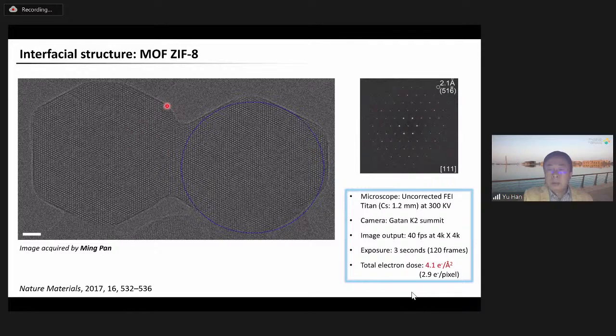Okay, in the previous slides, I showed you that under the normal conventional TEM conditions, we cannot see anything in the image because the structure has been completely damaged, right? And now, using the low dose TEM, we keep the electron dose at a very low level. In this particular case, the total electron dose is only 4.1 electrons per square angstrom. So at such a low dose condition, you see the crystal structure of ZIF-8 can be very well preserved. So this is a very sharp contrast to the previous example. And this very well demonstrates the power of the low dose technique.